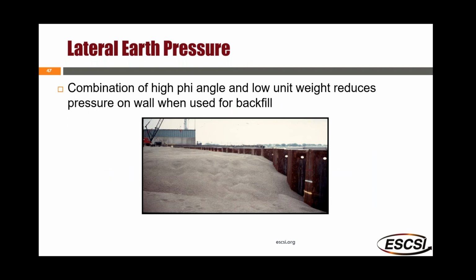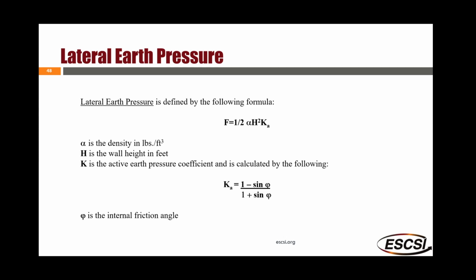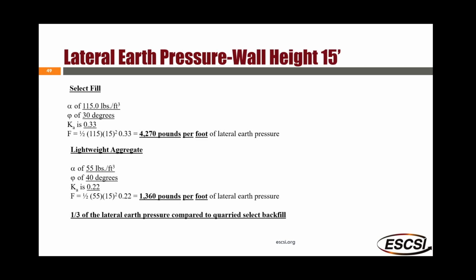The combination of high internal friction angle and low unit weight considerably reduces lateral earth pressures on walls. Lateral earth pressure is a function of the material density, the wall height, and a K value, which is a function of the internal friction angle. Running through the math comparing a select fill at 115 PCF with a phi angle of 30 degrees and a lightweight aggregate with a density of 55 PCF and a friction angle of 40 degrees, you get one-third of the lateral earth pressure compared to a quarried select fill. That can be significant when the design of components is taken into account.